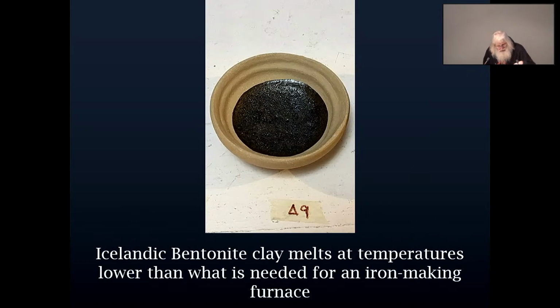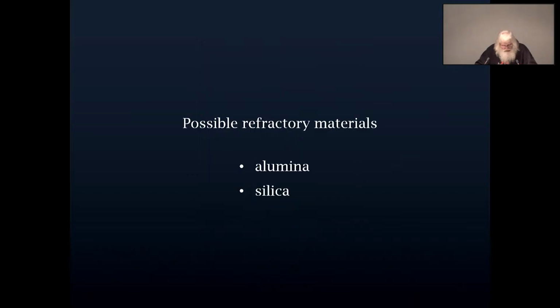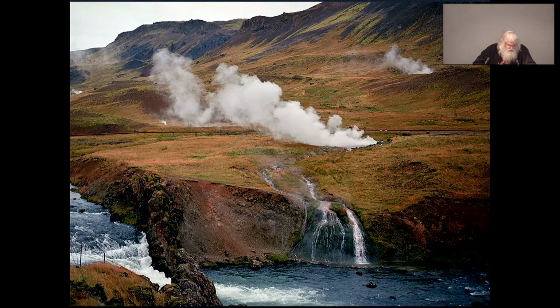Very simple tests showed us that Icelandic clay melts at the kinds of temperatures we need for making iron. So we needed to find something to add to the clay to make it resist that heat. We need what's called a refractory material to increase the melting temperature, and there's two good candidates, alumina and silica. Now, one possibility for these refractory materials is minerals at hot springs. And we did not turn here first. I freely admit it's not an area we investigated deeply. And perhaps our reasoning was wrong, but it did not seem that this material was readily available near all of the iron-making sites that we were familiar with.